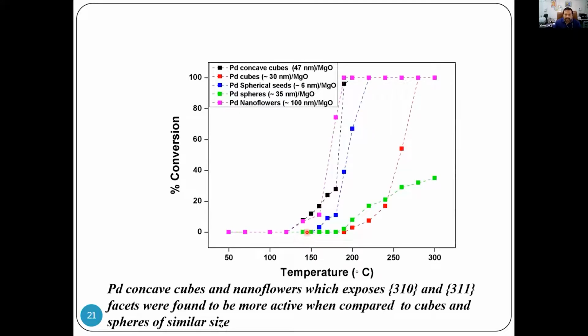We also carried out CO oxidation. So these are CO oxidation runs on a palladium concave nanocube supported on magnesium oxide. You also run this reaction with the small palladium nanoparticles, also nanoflowers. Nanoflowers are another class of material which shows very high index surfaces. And clearly, when you have nanoflowers and concave nanocubes, they have different kinds of reactivity trend, where the conversions reach 100%, close to 200 degrees Celsius. Whereas Pd spheres with 35 nanometers give only 30% conversion under 300 degrees Celsius. So again, a clear structure dependency or facet dependency is being demonstrated here.